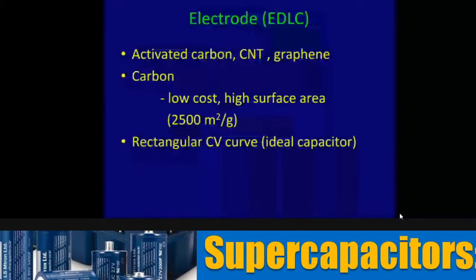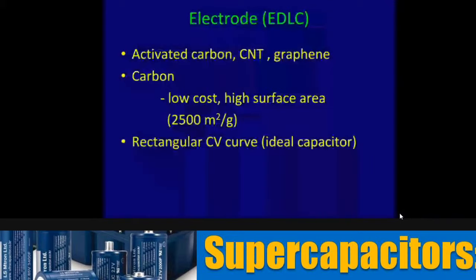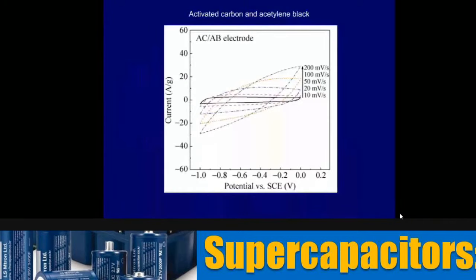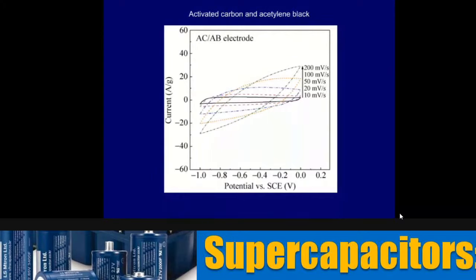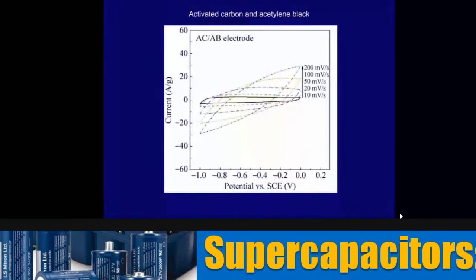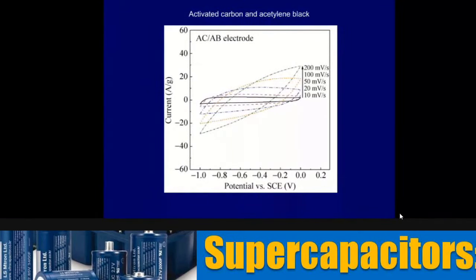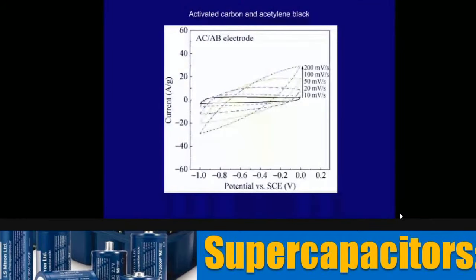And because this is a surface phenomenon between the electrolyte and electrode, the charging curve looks like a rectangular curve. I'll talk about CV a little later. CV is one thing that permits you to look at the charging profile. You can see here that when you keep on increasing the scan rate, the current increases, and most of these curves approximate more to a rectangular curve. You can see that the area is smaller at 10 millivolt per second. Area keeps on increasing, and you see that it's almost a linear variation. So I'm coming back.